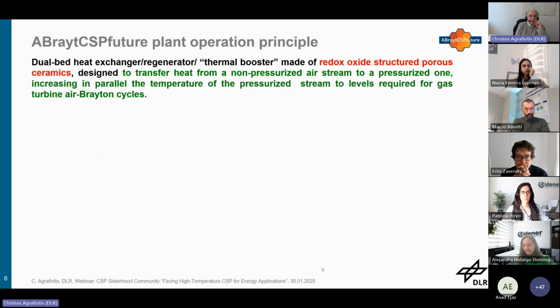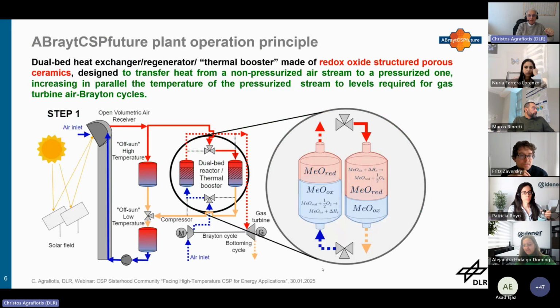So the same principle is used to design a heat exchanger regeneration thermal booster made of reactive redox oxide porous ceramics. We want to transfer heat from a non-pressurized airstream to a pressurized one and increase the temperature of the pressurized system. And this is how the concept would operate. From a receiver, we need to use a dual bed reactor system so that one oxide is reduced, whereas the other is oxidized. So the idea is that hot air reduces the oxidized oxide, to the far right. And in the other bed, the oxide is already reduced, so cold air is introduced, gets heated from the reduced oxide at the high temperatures to be driven, always hot air, to the gas turbine.